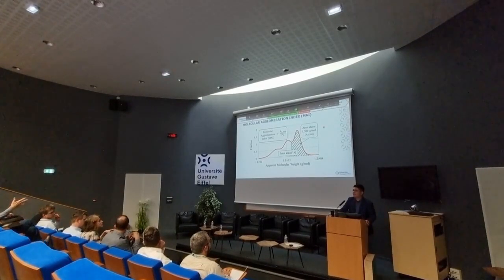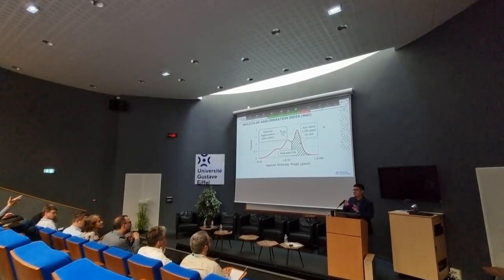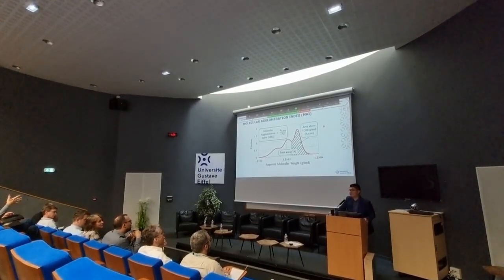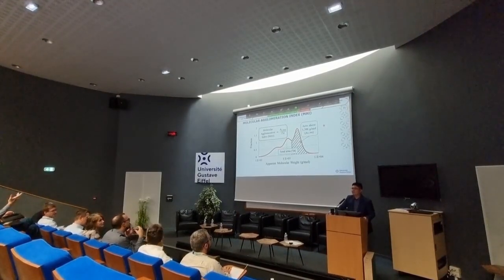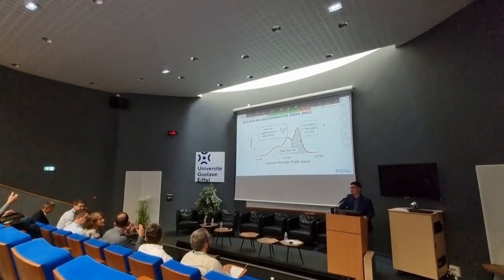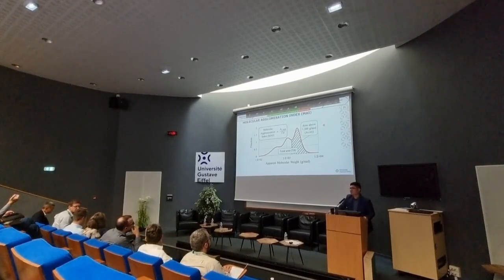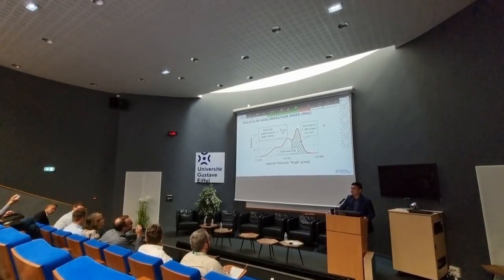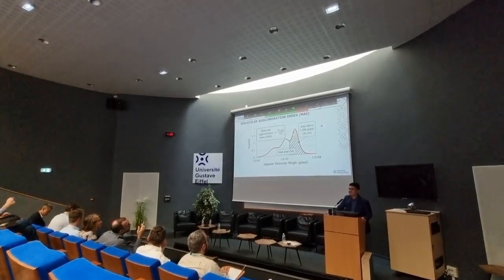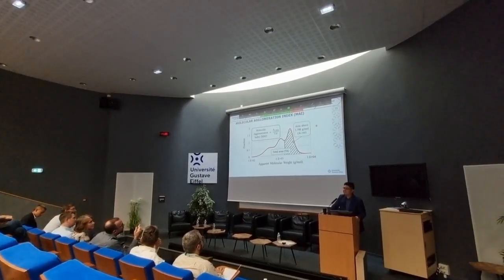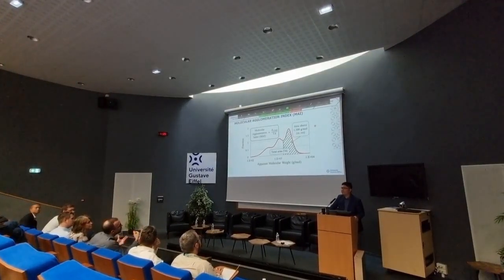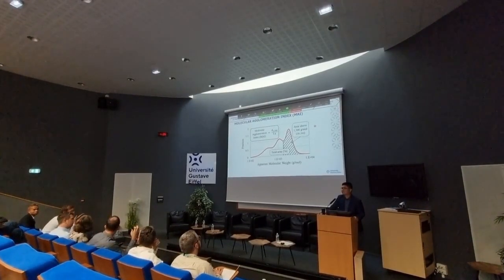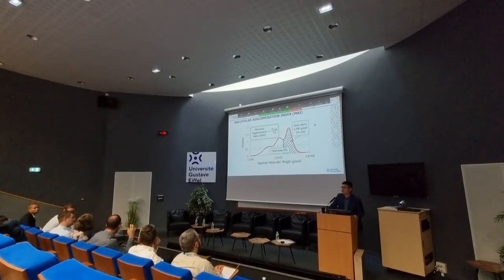Asphaltenes are big molecules, but they are able to agglomerate, to merge together. But I don't think that they are cross-linked as polymers. But they have a rather solid behavior. Yes, they're the structural part of it. So it's not only a fraction of high molecular weights, it's also a fraction of components that have what we call solid behavior.